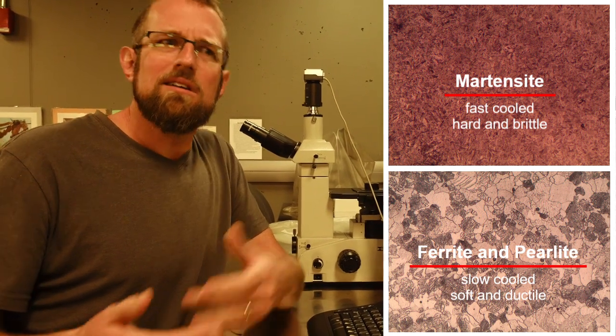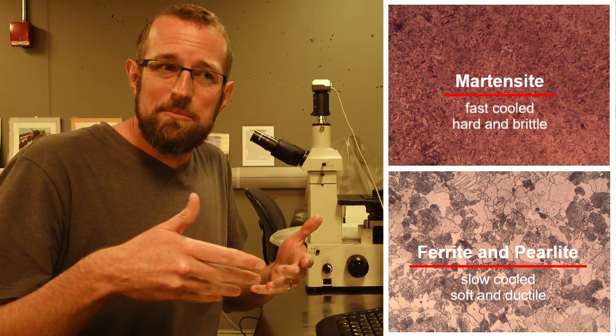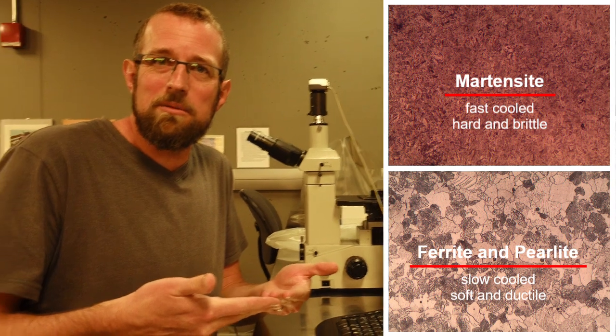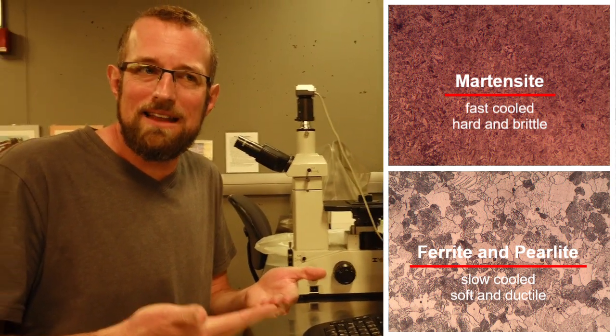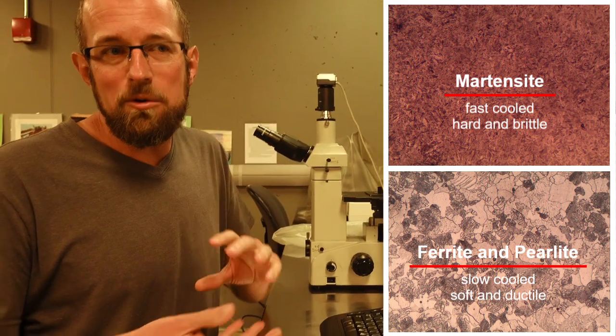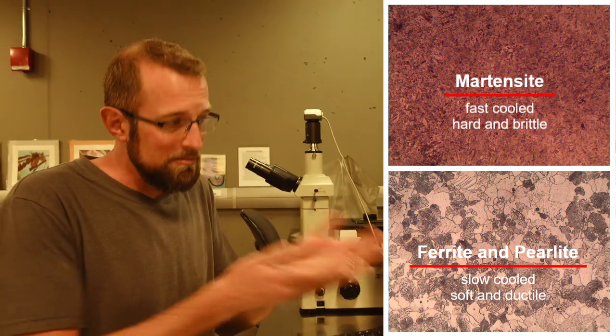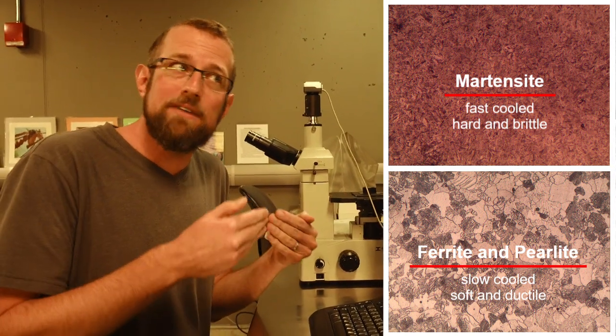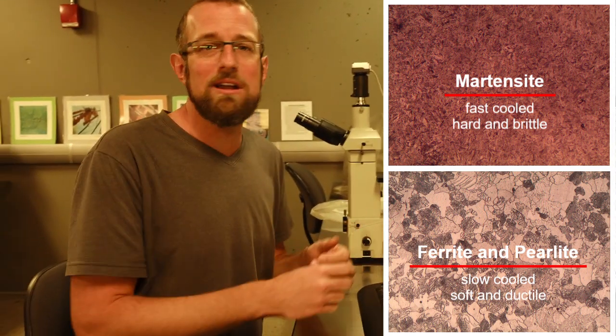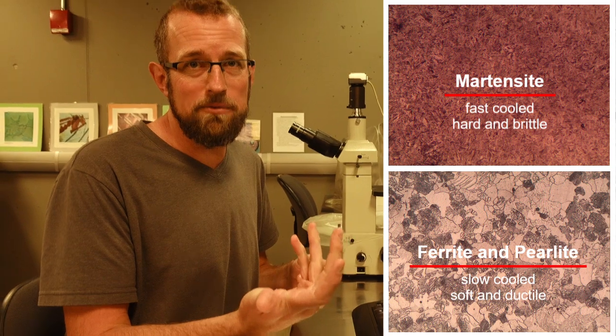Say I'm welding, for example. If I weld my material, I'm probably welding something like a structural steel in most cases. I don't want martensite to form. I don't want my material to be less tough or more brittle than it would be otherwise. And so when I'm welding, I want to make sure that I form ferrite. I want to know how fast I can cool my weld while still being safe. Because if I cool any faster than that, martensite might form and then I'm in trouble.